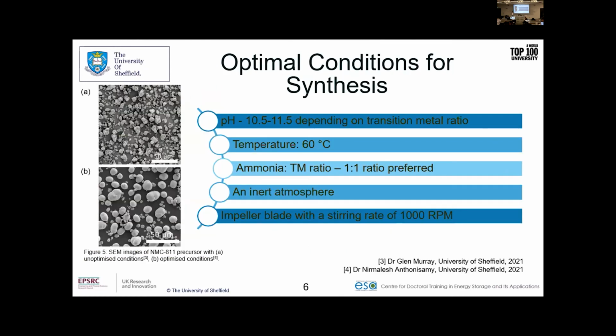So if we look at these SEM images, scanning electron microscopy, the lesser controlled particles are rather irregular. There's some bits of clustering from imperfect conditions, and some spherical particles, but they're not consistent, compared to when you look at the bottom, more optimized conditions, which are nicely controlled, and you can see they're a lot more symmetrical, a lot more uniform throughout the sample. And this is because we've optimized these conditions.